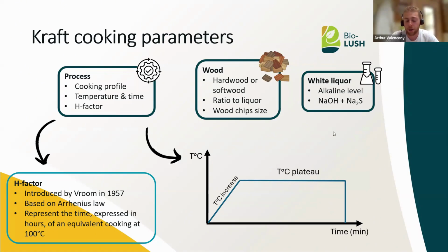Another interesting parameter is the wood, because as Sandra explained, we can have different types of wood, for example, hardwood or softwood, which are the main woods processed in the kraft process. Then the liquor to wood ratio, meaning the quantity of wood for a quantity of liquor introduced, will have an impact on the consumption of chemicals, for example. And the wood chip size: the wood chips are usually 3 to 5 centimeters square and around 5 millimeters thick. If you decrease the wood chip size, the chemicals can penetrate the chips more easily, but you will consume more chemicals. So this size needs to be controlled.